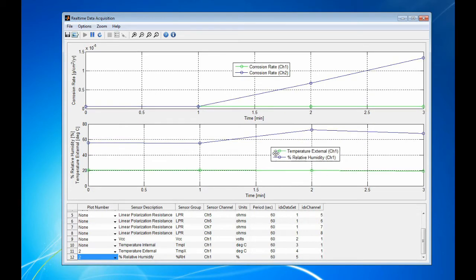Again, as more electrolyte penetrates the defective coating, the corrosion rate is increasing under sensor number 2, channel 2. And as time goes by and the electrolyte evaporates, the corrosion rate detected by channel 2, sensor 2, will start to decrease and come on back down to sensor number 1, which is the sensor under the protective coating, which is seeing minimal electrolyte intrusion. So this is to give you an example of how the system works with the host software and the sensors, their installation, and the AN110 unit.